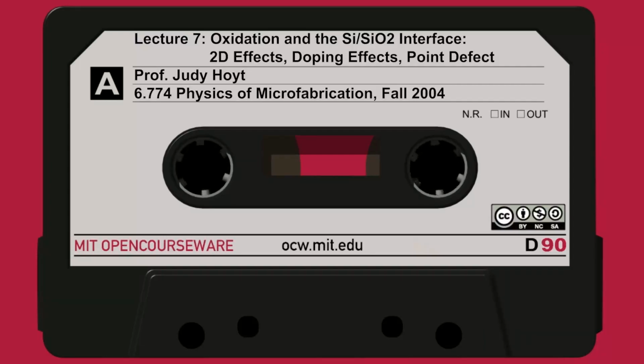So let's go on to slide 11. You can probably get the impression by now, there's no way you can easily do these calculations by hand. The Deal-Grove piece of cake: you sit down, you just simply solve or integrate the equations. They're all analytic. These are non-analytic. The shape of the growing oxide changes with time. K sub S, D, and eta all change with stress, and the amount of stress is changing with time as the oxide has to push on a thicker and thicker thing above it. So with all this time dependence, you really need a numerical simulator. You need a computer to do these calculations for you and to integrate them in time.